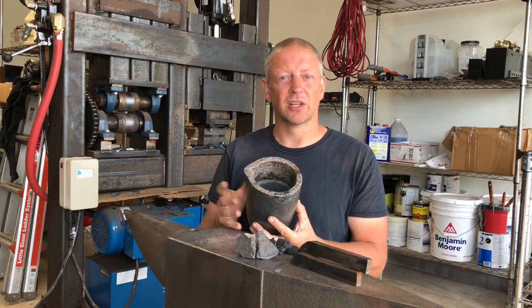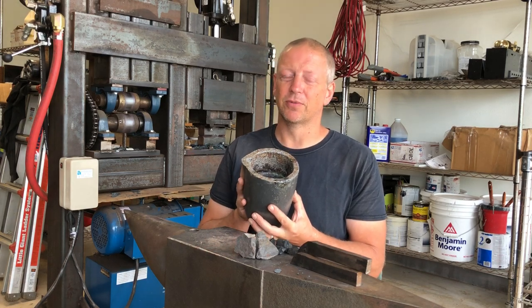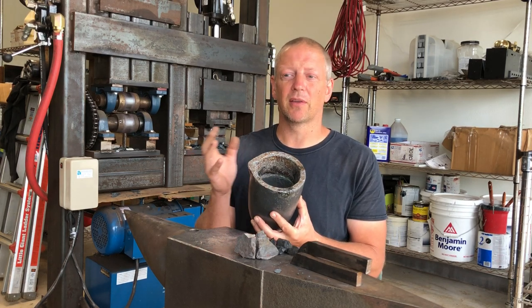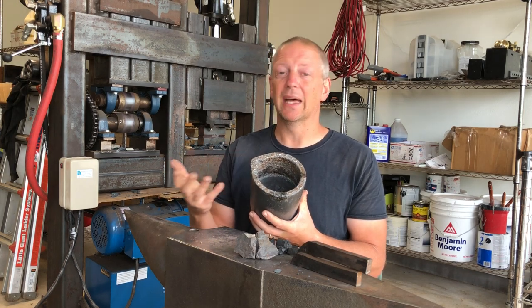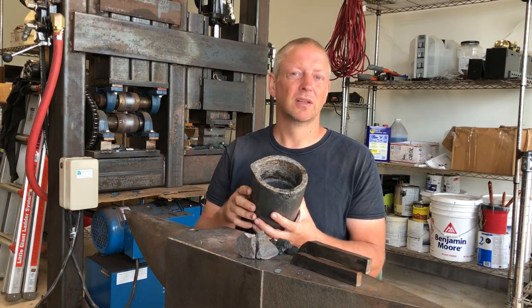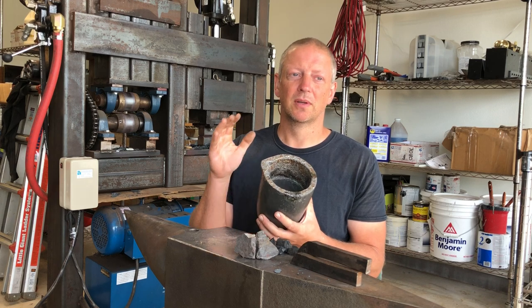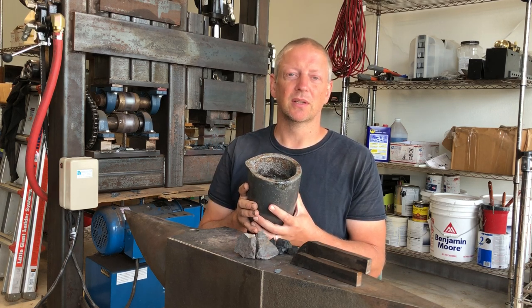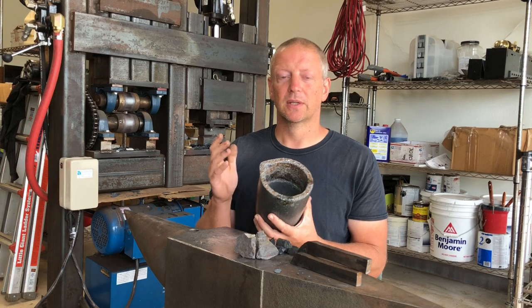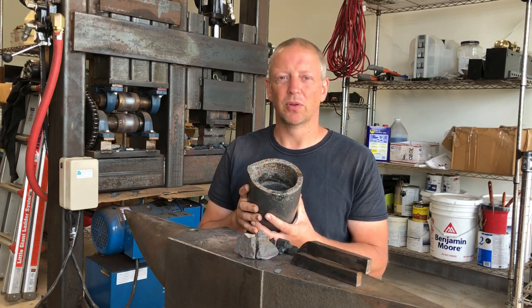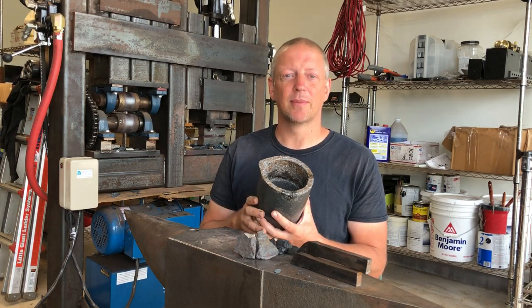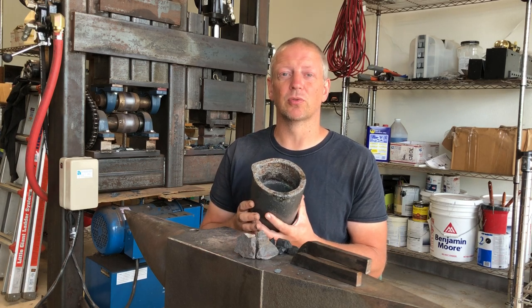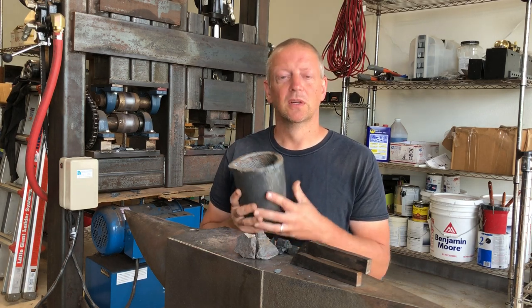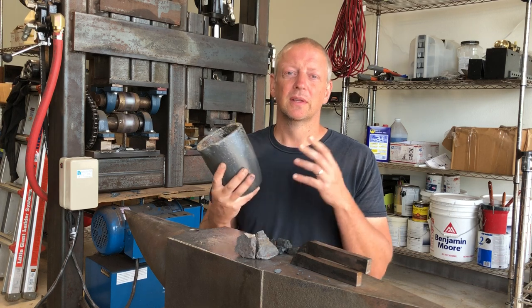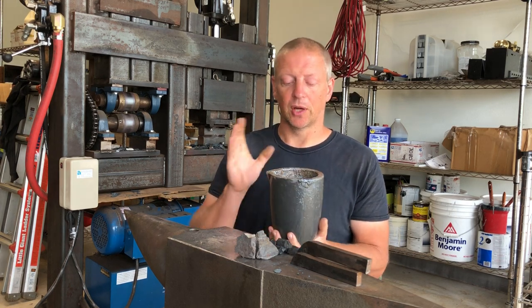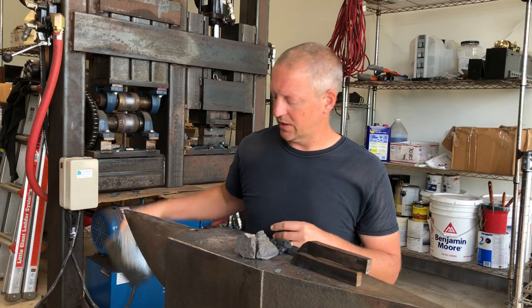Similarly, silicon carbide crucibles are not great for the crucible steel process, simply because, again, the molten iron can consume silicon carbide at a pretty rapid pace. With both of those, you're really going to throw off your chemistry. And in the case of pure graphite crucibles, from talking to folks who have used them, they don't last very long. So I'm going to set this aside for a minute so I don't knock it over.